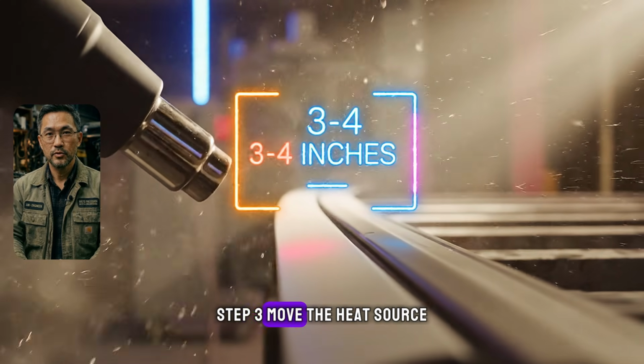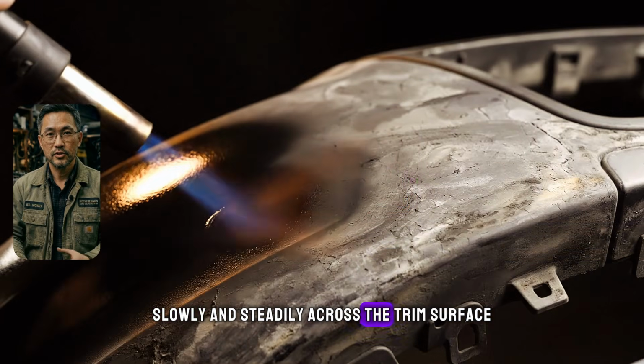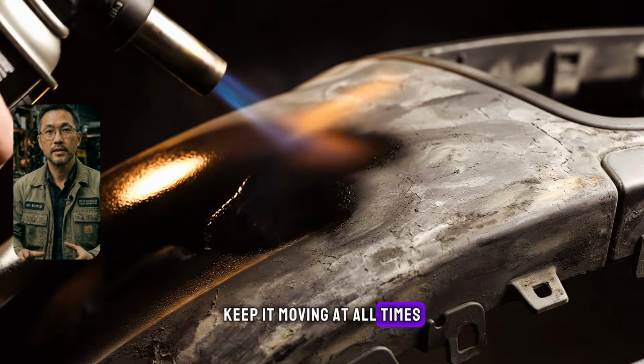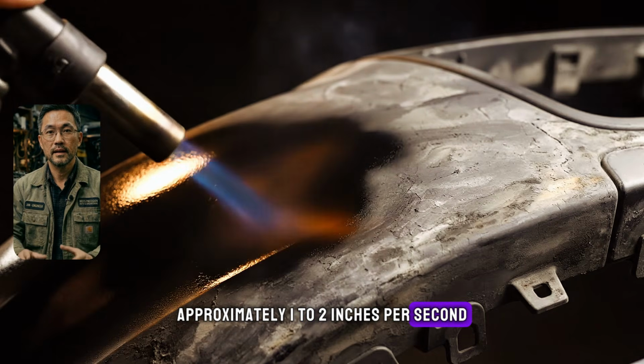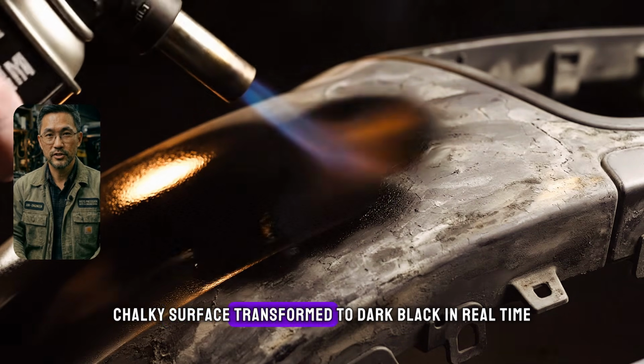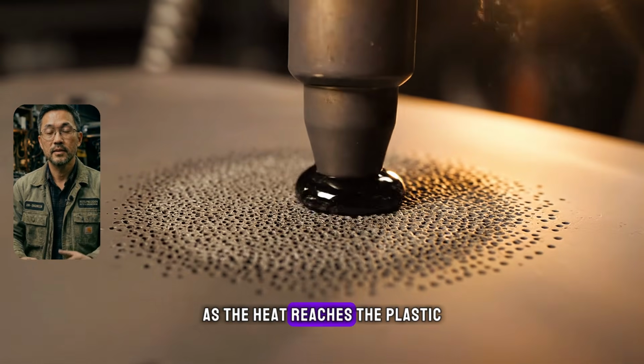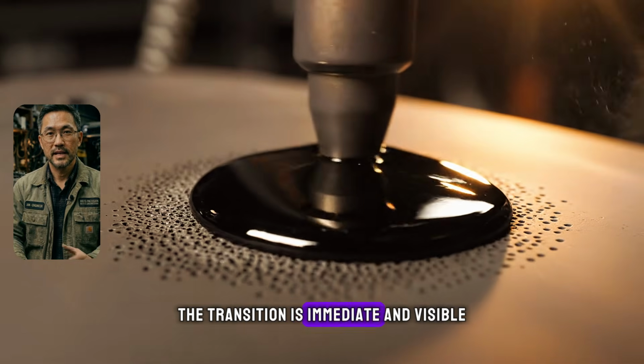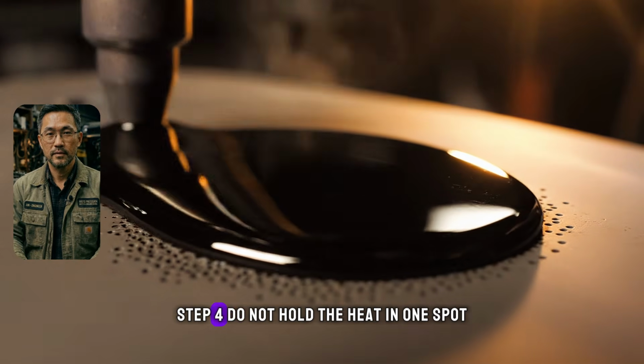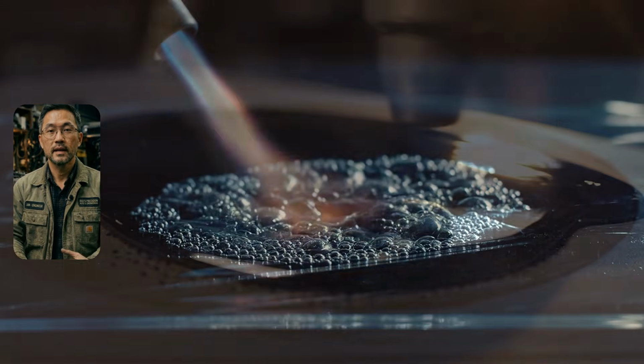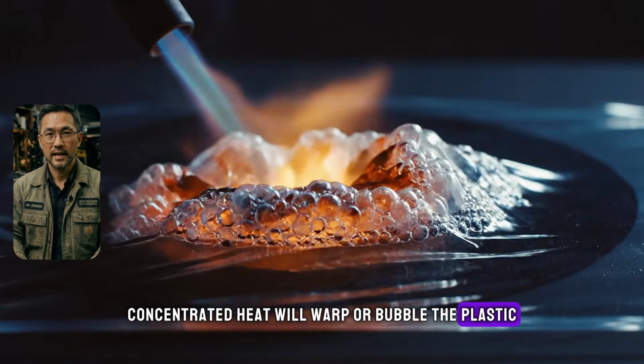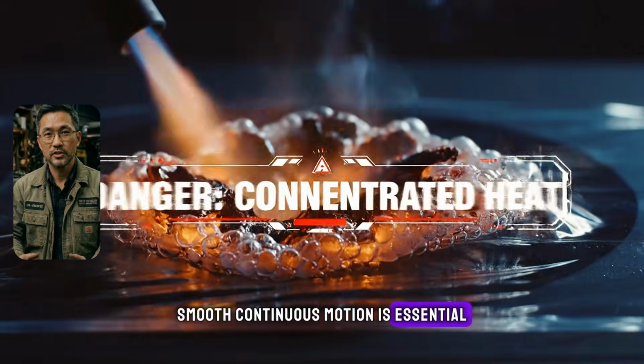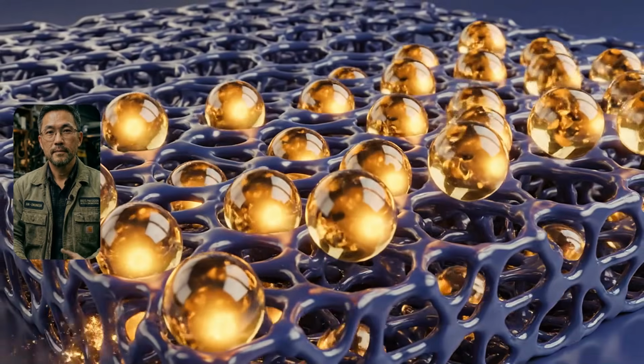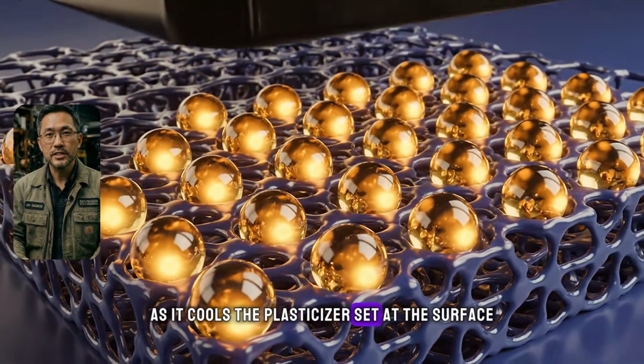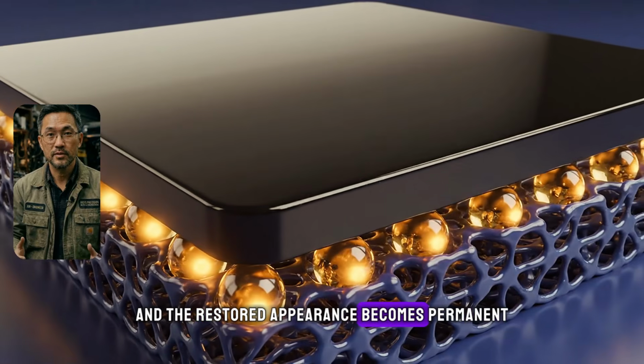Step 3. Move the heat source slowly and steadily across the trim surface. Keep it moving at all times, approximately 1 to 2 inches per second. You will see the gray, chalky surface transform to dark black in real time as the heat reaches the plastic. The transition is immediate and visible. Step 4. Do not hold the heat in one spot. Concentrated heat will warp or bubble the plastic. Smooth, continuous motion is essential. Step 5. Allow the plastic to cool completely before touching. As it cools, the plasticizer sets at the surface and the restored appearance becomes permanent.